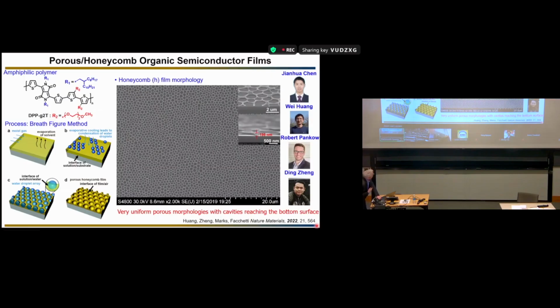So to answer the first question, what we did is we took an organic semiconductor that we knew works well in an electrochemical transistor. And then we fabricated a film which has porosity. This is the SEM of this film, which has been spin coated in a very high relative humidity atmosphere, on the order of 95%.